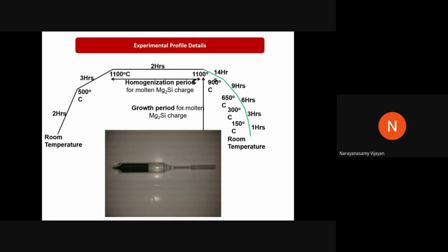You can see, before that, we have to find out the experimental profile details. After that only can we grow a very good quality single crystal, because through the profile you will come to know many of the if and buts, many of the negative points, many of the positive points. If you know precisely the temperature profile of your furnace, then you can play. Now you can see this profile.